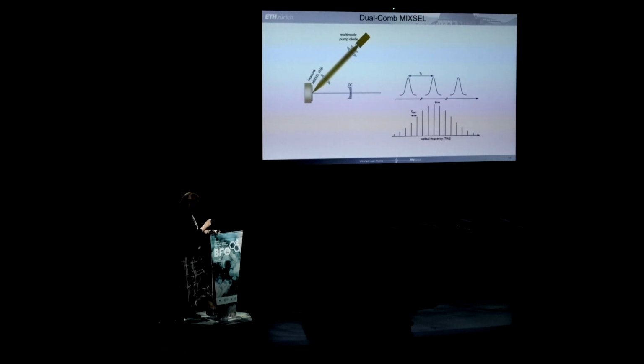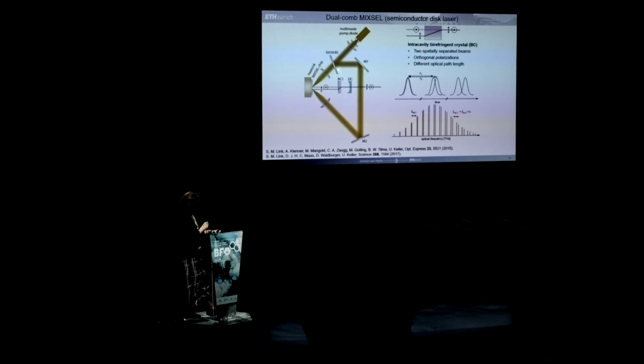So, as I said, you just pump this MIXSEL chip, then you get your mode-locked pulse train. And if you then add, next slide, a birefringent crystal, and you just pump 2 spots on the MIXSEL chip, you then get 2 mode-locked pulse trains with different polarization, because one polarization that is also a stable solution of this linear cavity is the extraordinary beam that goes a little bit of a different path through the birefringent crystal and therefore has a different path length. So, simple physics integrated into this device produces your dual-comb laser.